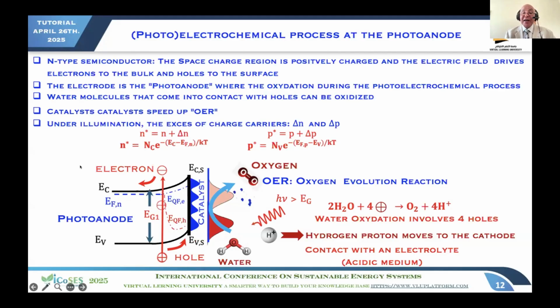You can't easily find a material with the kinetics to produce oxygen very easily when a reaction needs 4 holes. You have to have what we call a catalyst. That's what we put here in blue. So the oxygen evolution reaction is one of the key problems for water splitting without applying any voltage, just bringing the delta G, what I talked about, from this splitting of the Fermi level, or of the electrochemical potential. This is very important. That's the takeaway here.